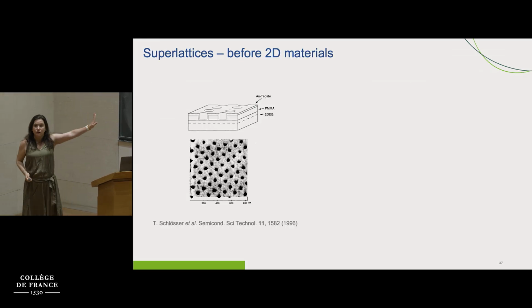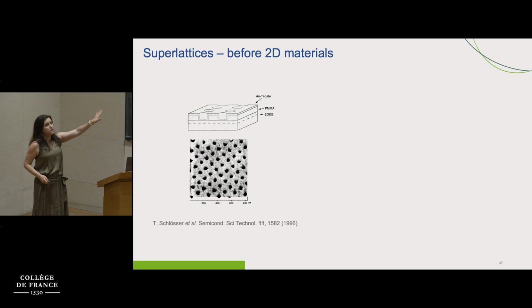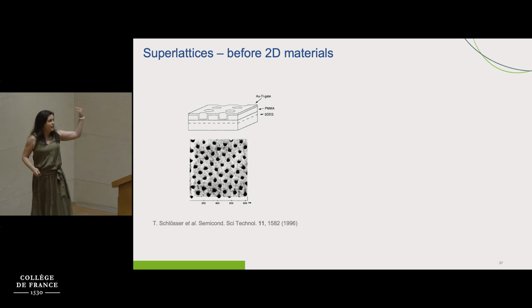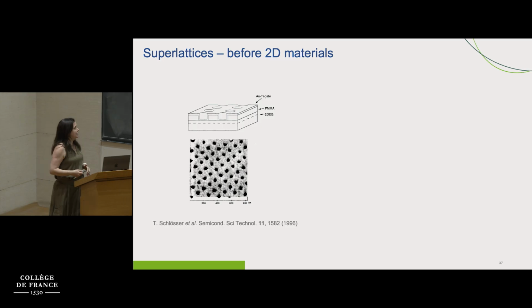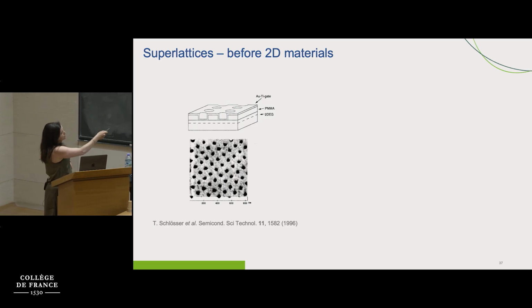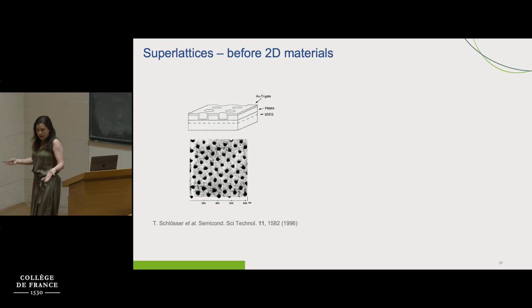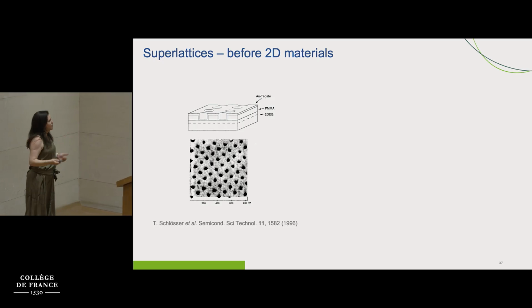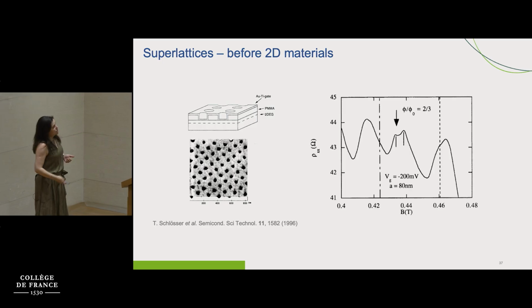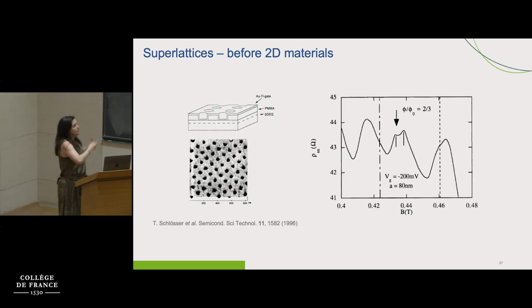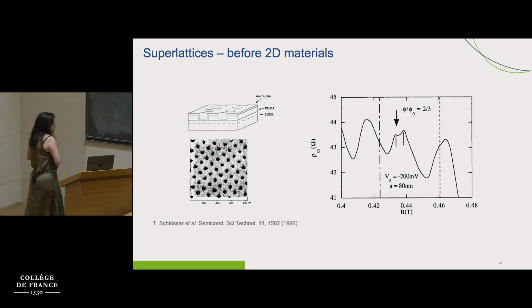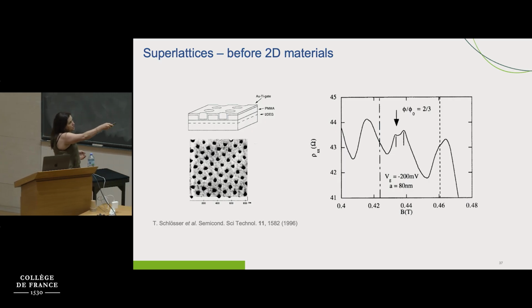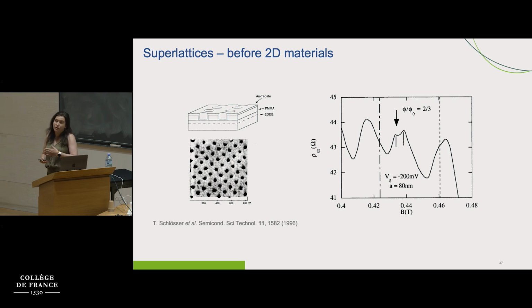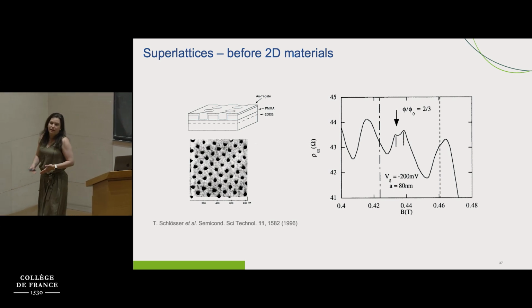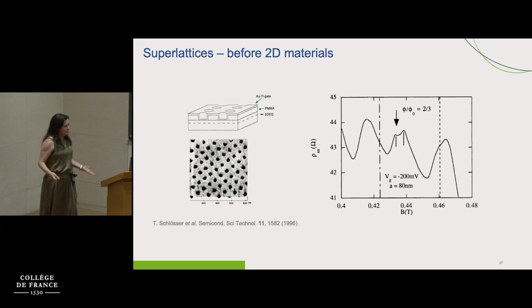Of course, graphene was not the first time that people tried to reach this limit of the Hofstadter butterfly. There are measurements that date back to the 90s, where they used gallium arsenide heterostructures and patterned holes on this to try to observe the effects of having a superlattice. In this case, the superlattice is much larger, around 80 nanometers. And with the technology available at the time, they managed to see some signatures of the Hofstadter butterfly. However, the disorder was too large, and they couldn't see anything more clear.